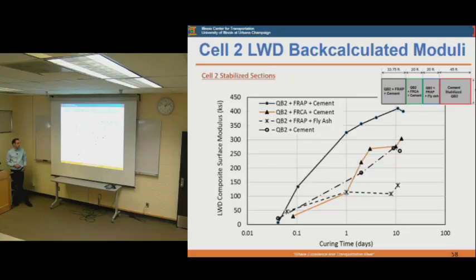So we were investigating the LWD modulus and how it is changing with curing time, or the number of days between construction and before the HMA was paved, for the different test sections, and how it compares for the different test sections. In some sections, like the one that had the QB with the FRAP with the cement, we were back calculating a modulus of up to almost 410 KSI on the top of the layer. For the other sections, they were lower, and especially the one that had the fly ash had the lowest modulus of all of them after almost 10 to 14 days, depending on which section was constructed first and last for the different test sections. And that was for cell 2.